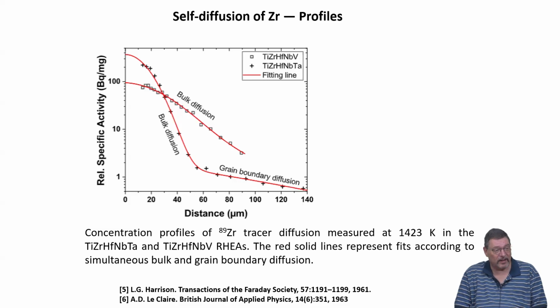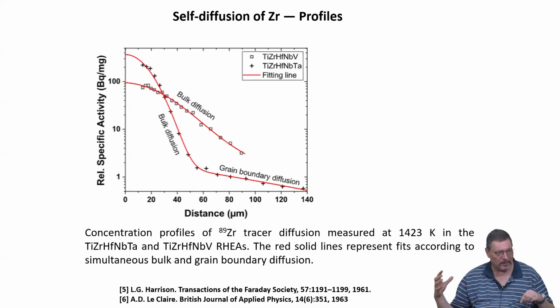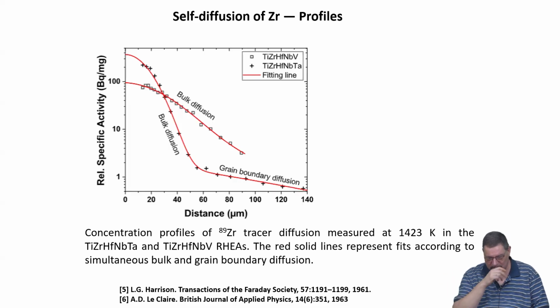And it's because, again, also of the smaller atomic size of the vanadium, so it fits much nicer into the remaining constituent elements, while tantalum is a very large atom, right? So it creates a lot of local atomic-level stresses, and that can also accelerate phase formation. And the idea here was to replace this by a smaller one and see what this does. So that will give toughness also. That will give also toughness, yes.